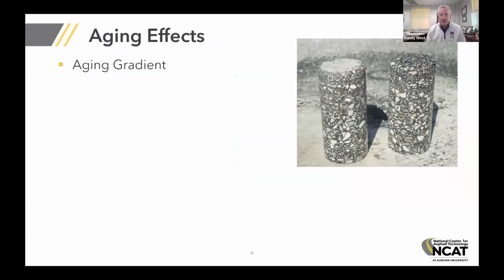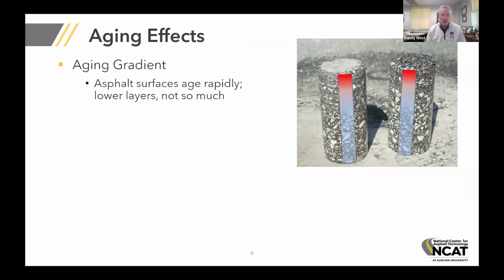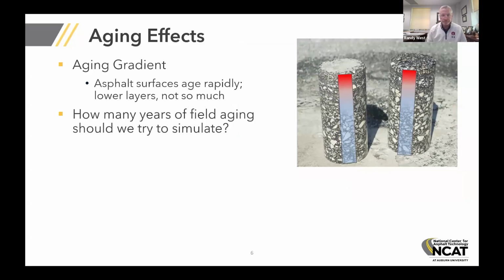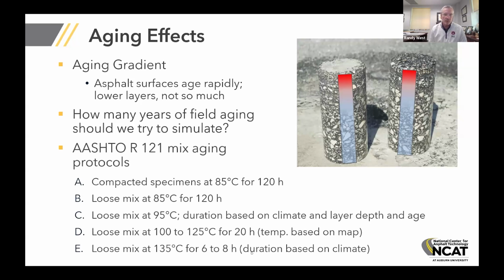So a little bit more on aging effects. One of the things that there's certainly some research on, but maybe it's not well known, is asphalt pavements age, and they age from the top down. In fact, the asphalt surface layers, the top inch or so, ages significantly and rapidly, but the lower layers really don't age very much. And that's important when we start thinking about laboratory aging of mixes to simulate the field. Okay. Then we have to ask the question of how much field aging are we trying to simulate? How many years of field aging is important? Is it 1 year, 2 years, 10 years?